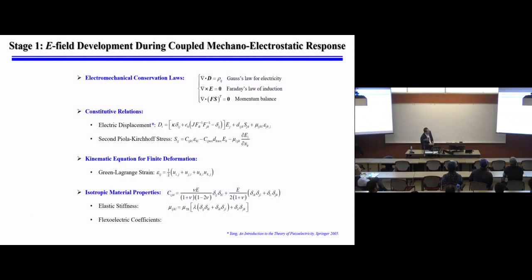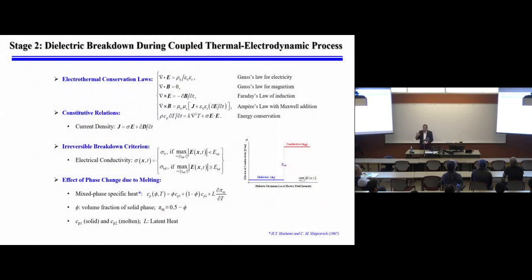Quickly, to point out the governing equations here. Electromechanical part, it's still the same equations that I talked about previously. The electro process is very fast, it's almost equilibrium. That's the mechanical process. We still have the same set of equations, except that in this case we have piezoelectricity as well. Right, same set of equations. Now, during breakdown, the electrical process is very fast, so we have to use the four Maxwell equations.